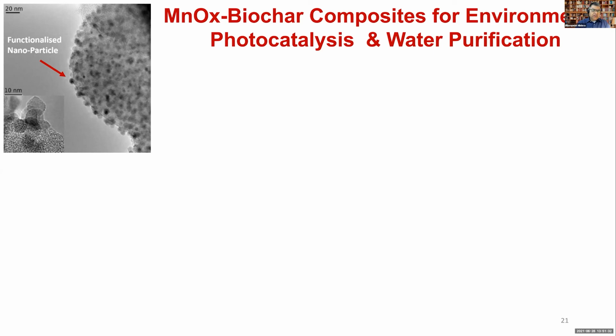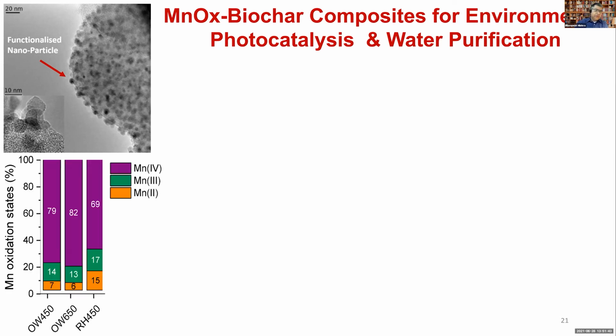But forming true manganese oxide biochar composites is not straightforward, because carbon itself, in this case biochar, has its own electron shuttles and so on. So we have been able to do that after 2 years of failure, and finally we have what is truly a manganese oxide biochar nanocomposite, and you can see some of these high resolution TEM images for the surface particles, and we conducted these experiments for different kinds of feedstocks.